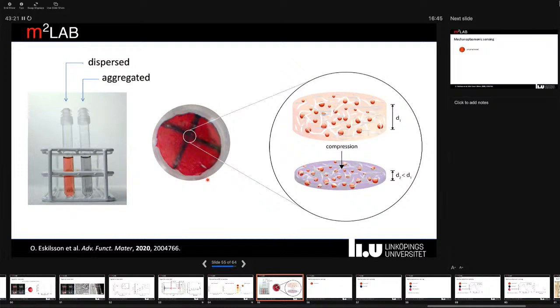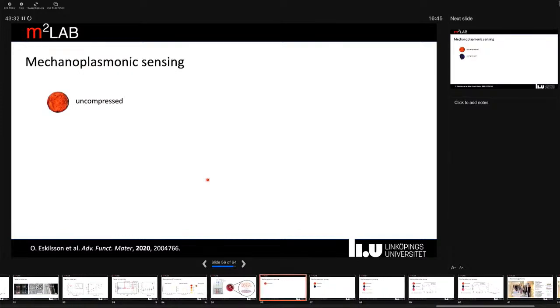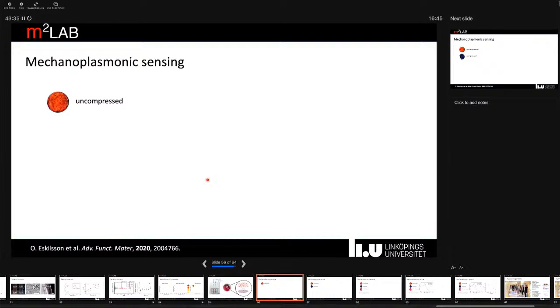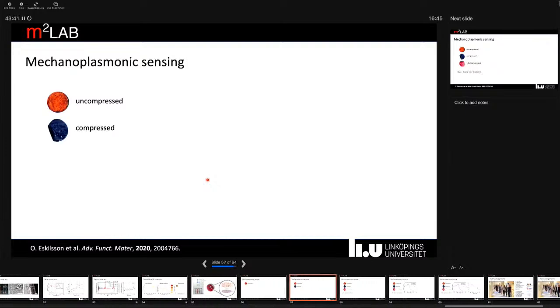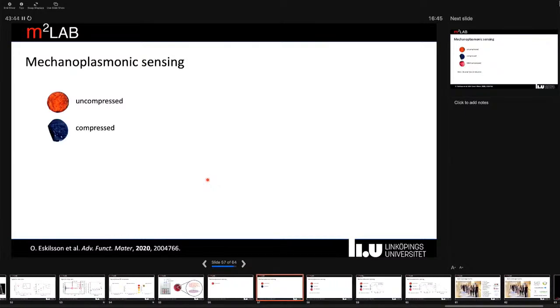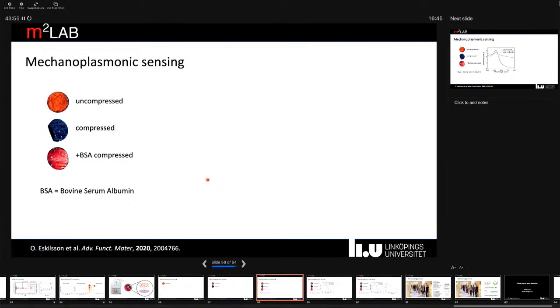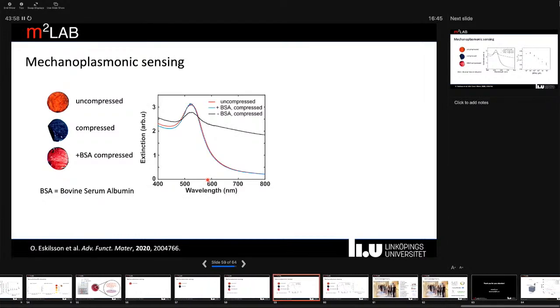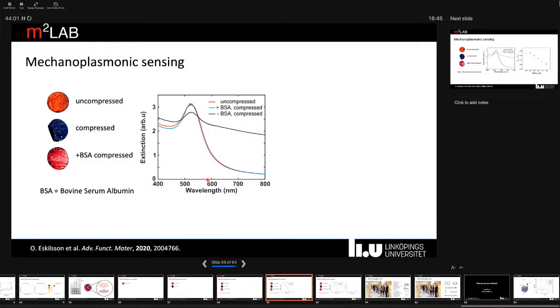So this is essentially just an effect of pressing or compressing the material and making the particles immobilized on individual fibrils come close enough for us to get plasmonic coupling. And we started exploring what could essentially influence this mechanoplasmonic coupling. So when comparing an uncompressed material with a compressed material, we see quite distinct color differences. But if we immobilize a protein, or just by physisorption on the particles before we compress, we don't see much of a color change. So essentially, the proteins here can prevent the particles from being mechanically forced into contact.